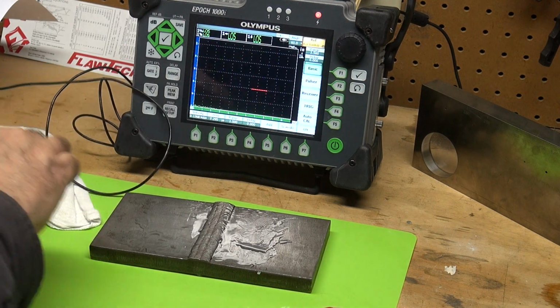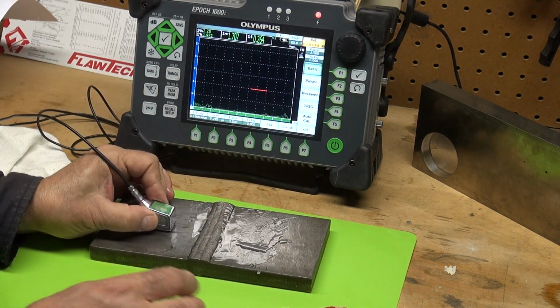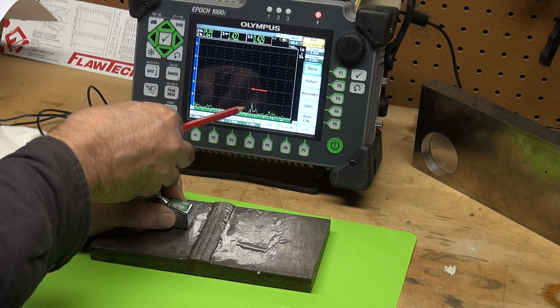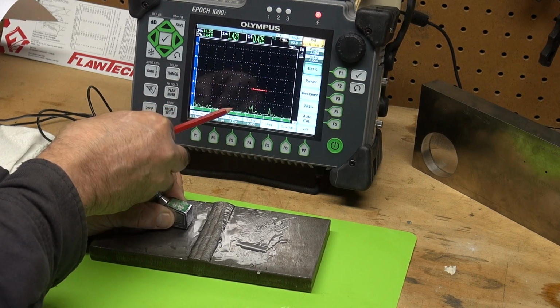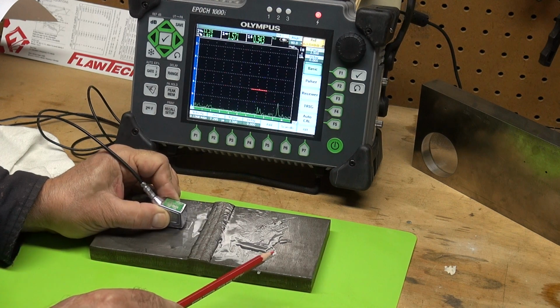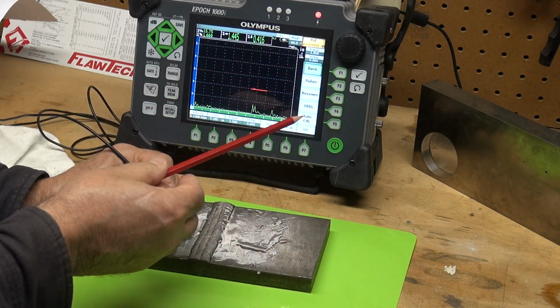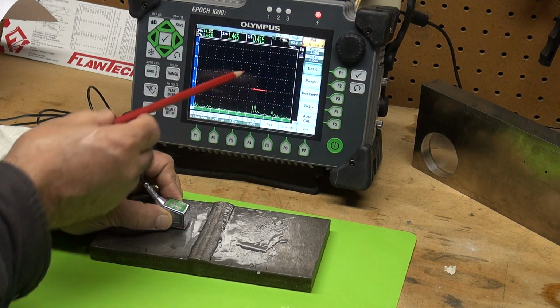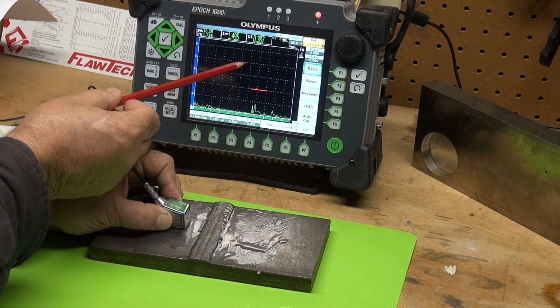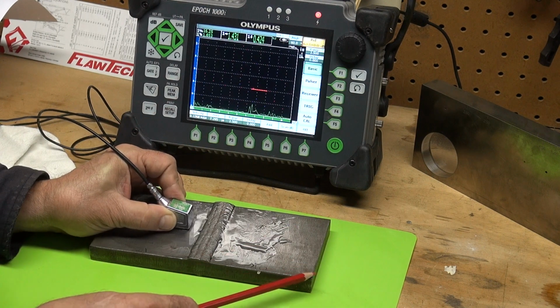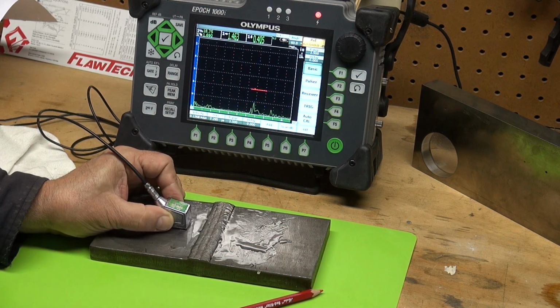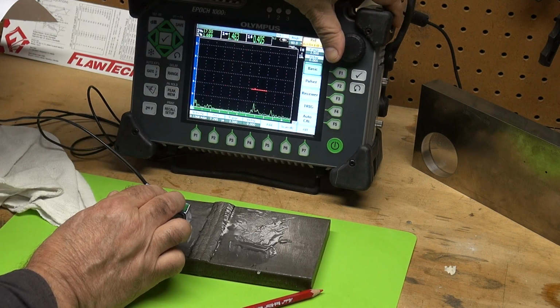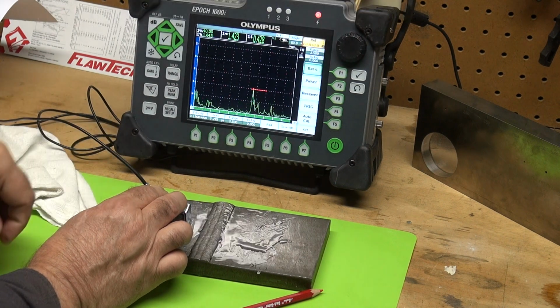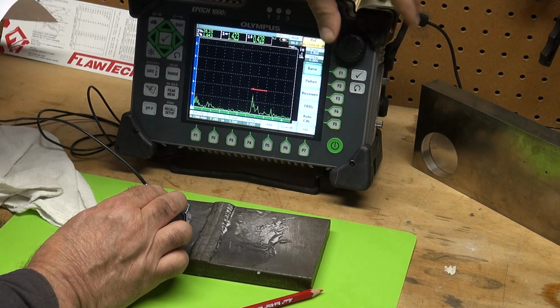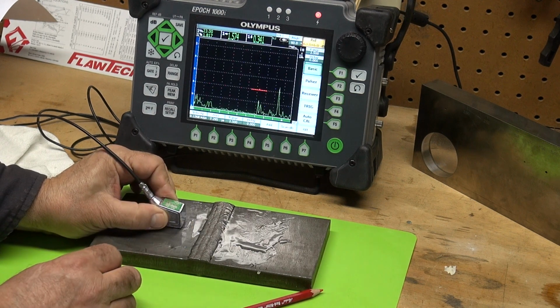Let me come over on this side, get my hand out of the way. You see, there's not a whole lot. It's very low amplitude. I'm only about 20% full screen height. And when I calibrated and set my reference level for the side drilled hole, I set it at 80% full screen height. So you see, it's fairly low amplitude. So that's another reason why you want to run, when you're scanning, depending on your code, like 6 dB hot. Right now, I'm adding 6 dB to my reference level, and that's pretty good.